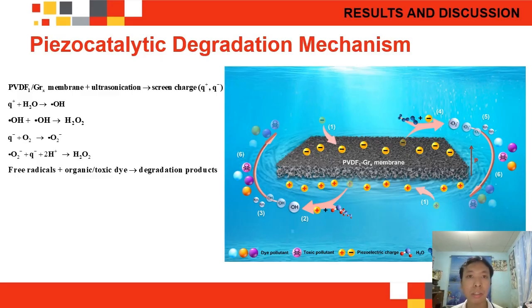Along with the change of membrane's strain, a portion of free charges will be released into the environment, reacting with H2O and O2 molecules to generate the hydroxyl and the superoxide radical. It's also worth mentioning that hydrogen peroxide was also observed by semi-quantitative tests. The generation of H2O2 may enhance the piezocatalytic performance. Hence, after the generation of free radicals by piezoelectric field, the free radicals not only produce hydrogen peroxide, but also subsequently degrade pollutants. The dynamic piezoelectric fields can keep this reaction process continuous, achieving simultaneous pollutant degradation.